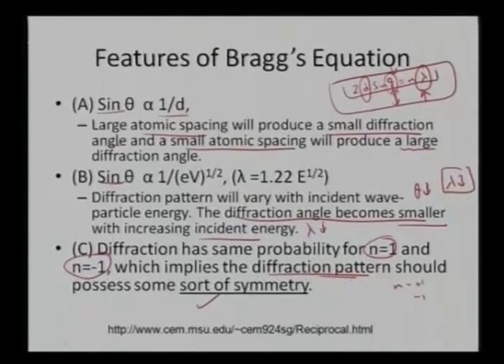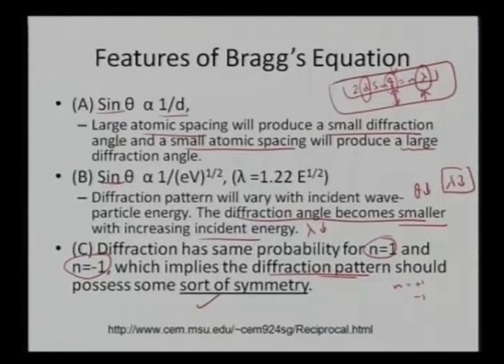Summarizing: if I keep λ constant, sin θ and d have inverse proportionality. If d is constant, θ and λ have direct proportionality — reducing λ or increasing energy gives a very low θ value. That tells us where the diffraction spots will appear in terms of Bragg's equation.